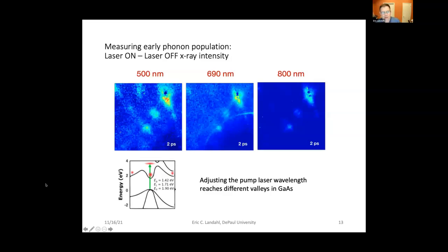First check was done of the basic idea that we are in fact bringing electrons to different valleys. As we increase the laser energy from 800 nanometers to 500, we seem to have preferential filling of different valleys. And remember, this is measurements that come from looking at phonon population and not anything's known really about the electrons. But it does become clear here immediately, 2 picoseconds at least after excitation, that we populate the different valleys differently by choice of laser wavelength.